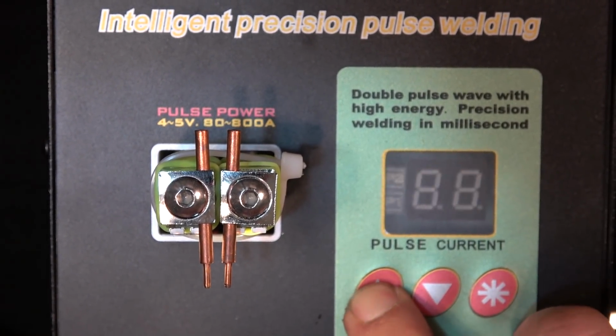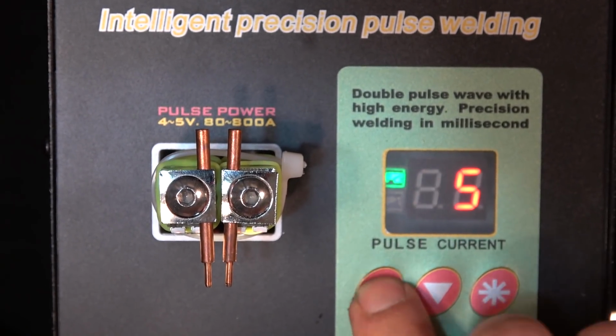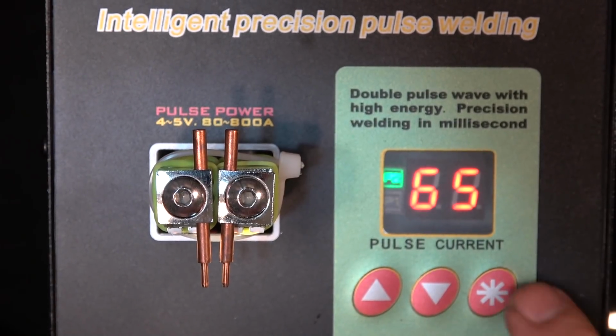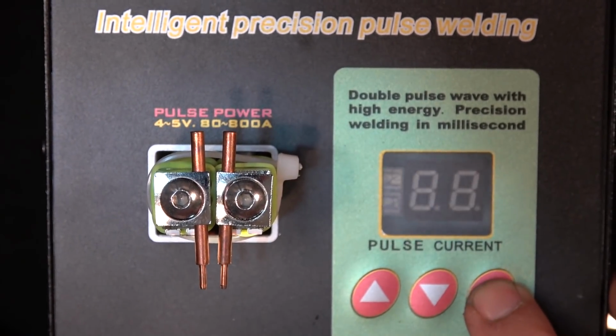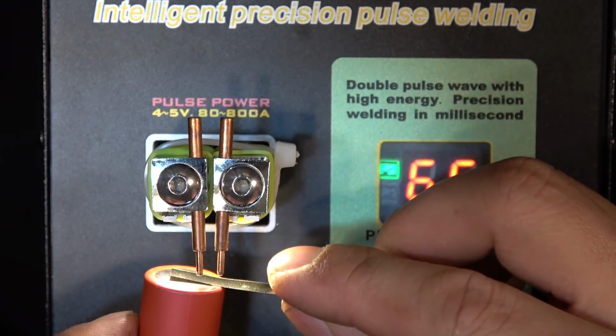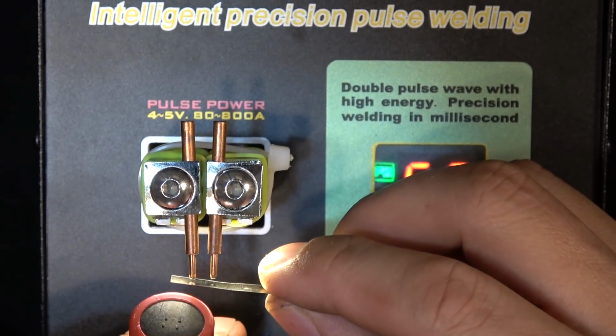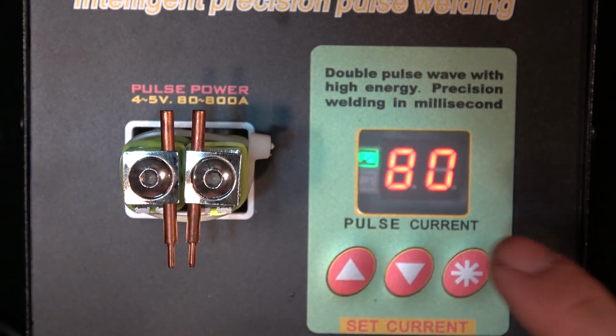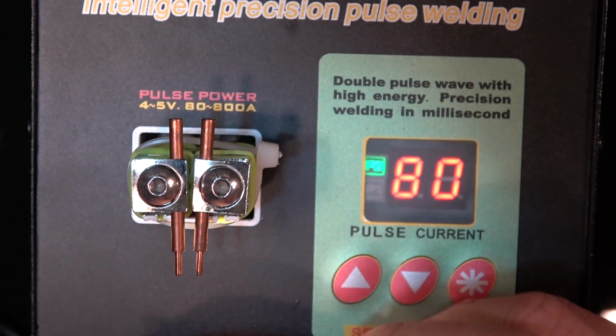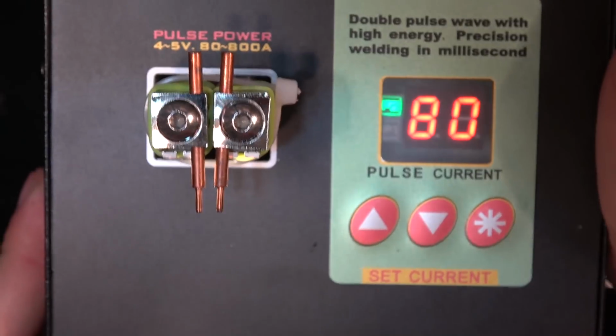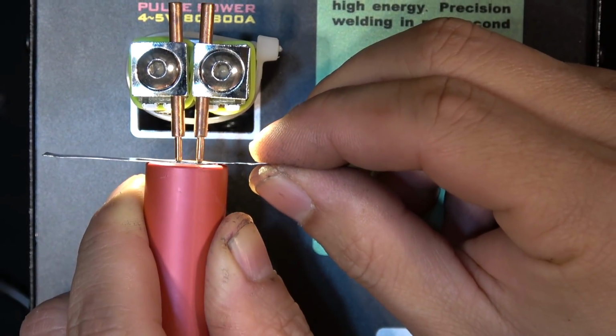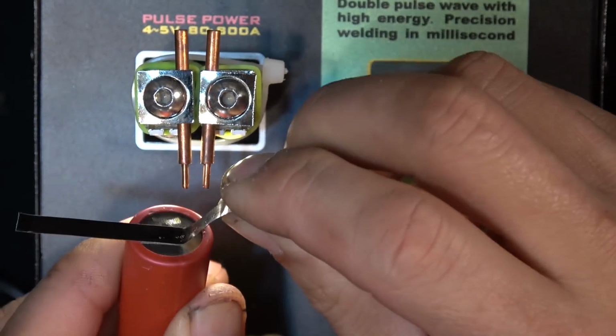And then I increase the current up to, I would say, between 65 and 70%. So let's try 65 first, see if it works. Okay. See, it doesn't stick. So just increase the current to 80%, and I've turned the knob a little bit, so increase the pressure on the welding spot here. Let's give it a try. Solid weld. I can't pull it out.